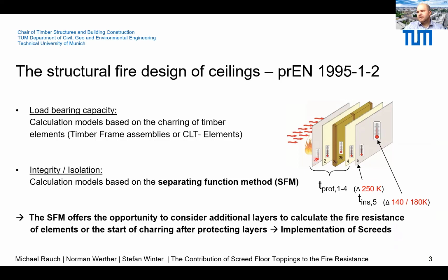For all the layers in the construction, we calculate a protection time with a temperature criteria of 250 Kelvin. And for the last layer, we calculate an insulation time with a temperature criteria of 140 Kelvin in the middle and 180 Kelvin at one point, maximum temperature increase. The sum of these times leads to the insulation time of the whole element.